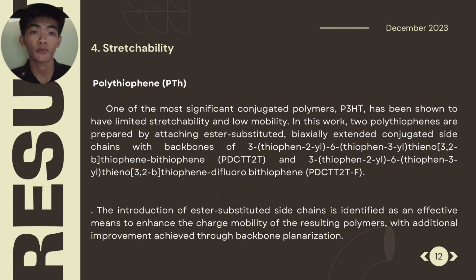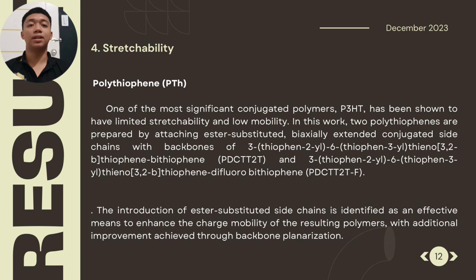Stretchability of polythiophene. One of the most significant conjugated polymers, P3HT, has been shown to have limited stretchability and low mobility. In this work, two polythiophenes are prepared by attaching ester substituted biaxially extended conjugated side chains with different backbones. In the investigation of the mobility-stretchability relationship of ester substituted polythiophene derivatives, the researchers find that the arrangement tendencies and stacking structures of polythiophene can be precisely adjusted through modification in side chains and backbones. The introduction of ester substituted side chains is identified as an effective means to enhance the charge mobility of the resulting polymers, with additional improvement achieved through backbone planarization.